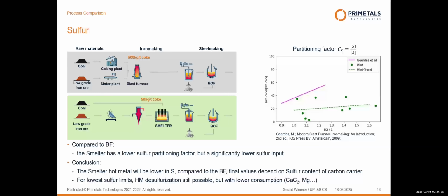Second topic is then the partitioning factor. Where is the sulfur going? Does it report to the metal or does it report to the slag in our aggregate? And there we see the partitioning factor for the smelter is about half to 1/3 of the factor for the blast furnace, meaning for the smelter, due to the different reducing atmosphere and the different kinetics, more sulfur is reported to the slag, but we have less sulfur input. That's why typically, on average, we could say in the smelter we have about 1/3 of the sulfur content that we have in the blast furnace.